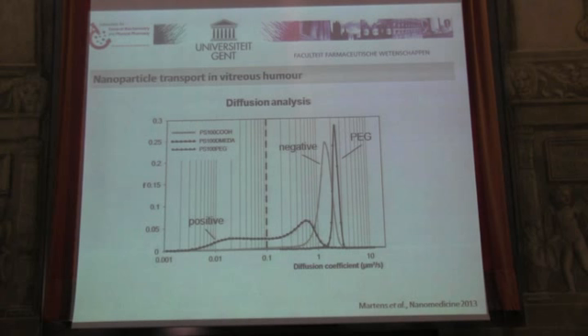And this could be quantified indeed, so the PEG mobility is very high. Negatively charged particles have a little bit lower mobility, and then positively charged particles, but this is actually what is mostly being used, cationic particles for gene therapy. They have an interesting bimodal behavior, so lots of them get stuck. They get stuck to the collagen fibrils, we found out. And then another part, and this is quite interesting, they are nevertheless mobile. And we figured out that this is very likely due to coating with the negatively charged hyaluronic acid molecules.